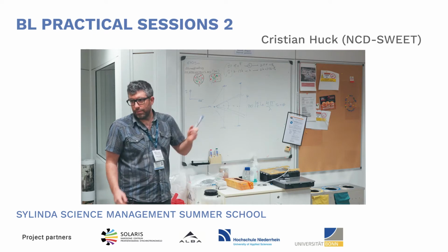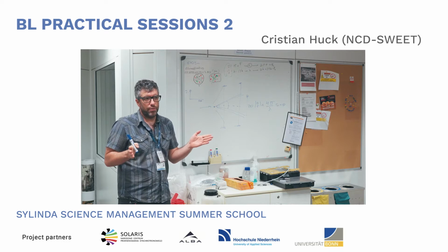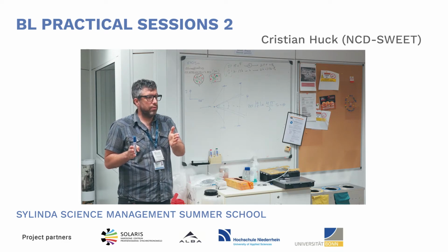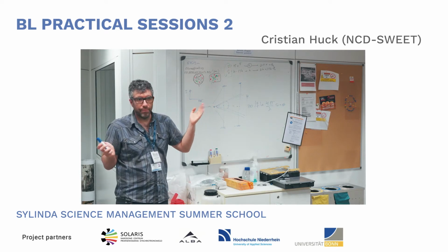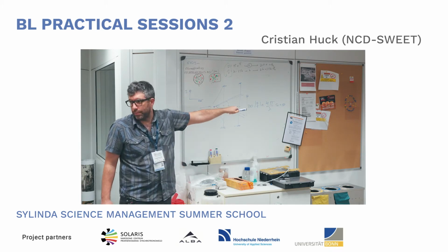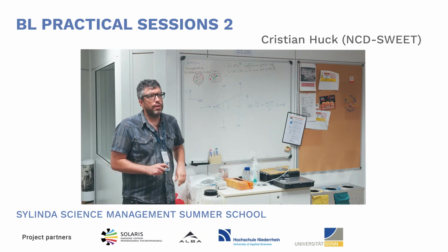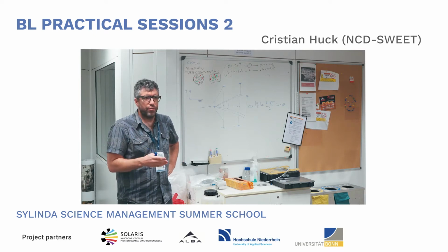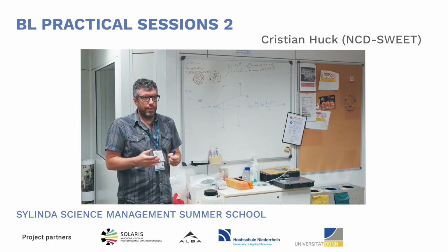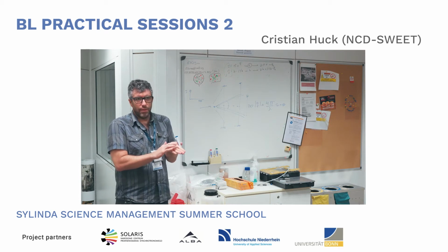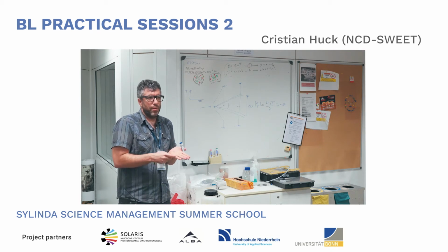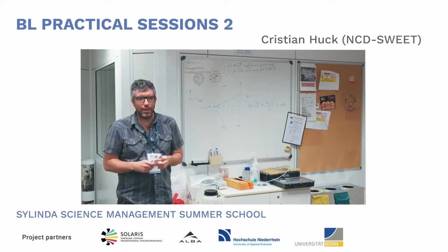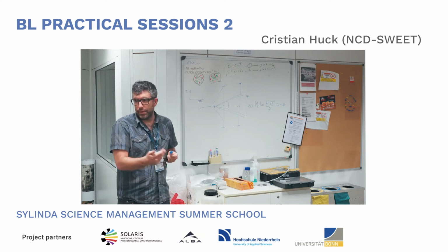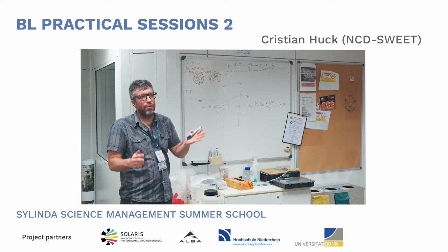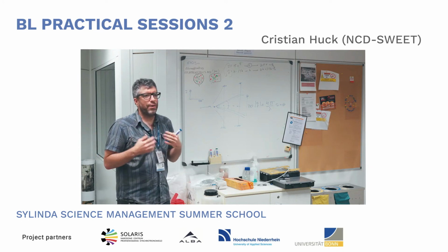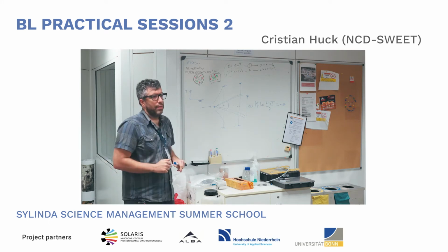So depending on the inhomogeneity size, you will choose a geometry, or you place the detector close to the sample holder or further away. So it depends. This is very important to know, because it's not the same if you come here and say, okay, I work with the chocolate factory, and you know for chocolate it depends on the polymorph of the fat, so the quality of the chocolate. Because this white thing is called blooming, one polymorph causes it and the other not, and it smells in your mouth and you are very happy. So it will depend on how you process the material with this info. Well, in that case, you have a diffraction pattern around 5 nanometers or something like that. 5 nanometers for us is small. So you place the detector close.